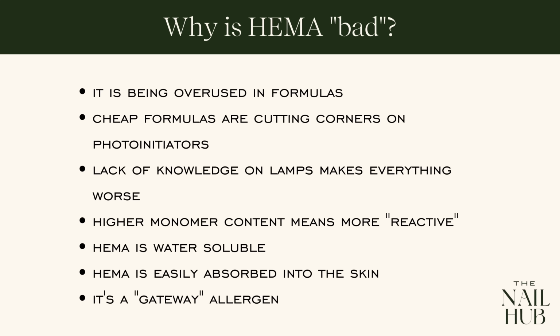Actually, when we're talking about the detail behind curing our UV gel nail products, or even our poly gels for that matter, if the lamp is not sufficiently curing our product, it can leave a ton of unreacted, unpolymerized monomer in our product, and that really exacerbates this whole HEMA and monomer conversation, because when we think the product has been cured on the nail, it actually hasn't been fully cured, and that can have long-term consequences.